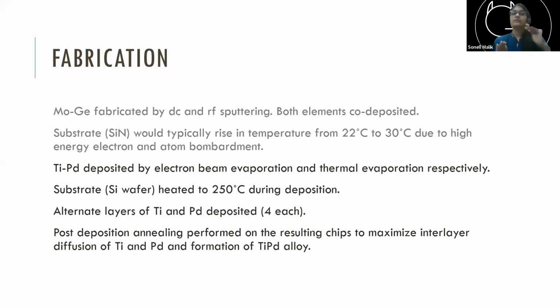So I deposited alternate layers of titanium and palladium. This was one of the first times we were trying to make an alloy out of alternate layers of two different materials. And to ensure that it did become an alloy, we did two things. First, when we deposited, we kept the substrate, the material on which we deposited the thin films, at a high temperature of 250 degrees Celsius.